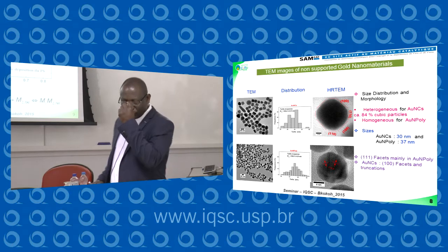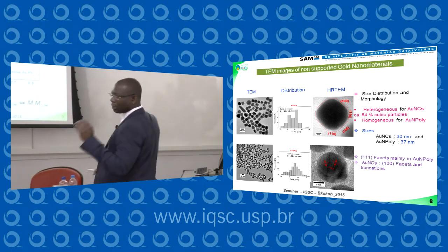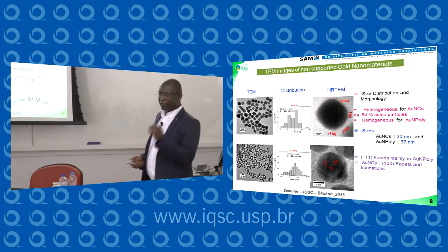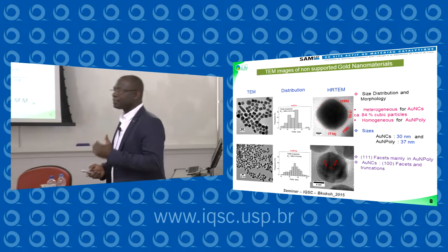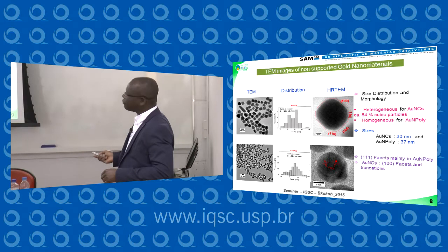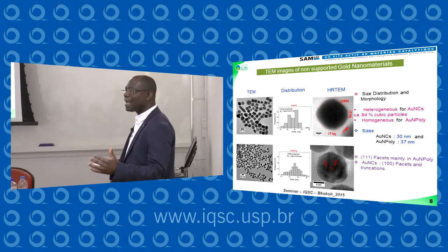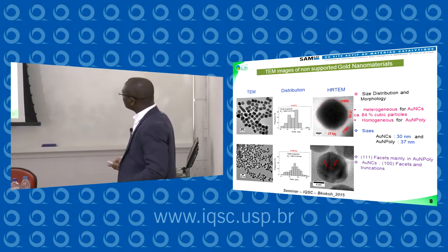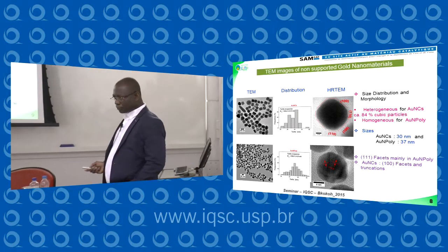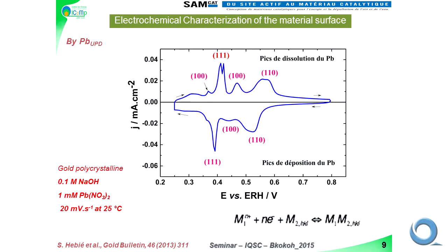It's the same in Alicante with Feliu. We take here, for example, a wire of gold, to reveal the orientation of the facets. This is the method of UPD, underpotential deposition of lead adatoms. By this method, you prepare this solution, and you apply a potential at 0.8. It's very important, because if you start here, you adsorb all the species at the surface, and you have to restart, okay? You prepare your working electrode, you immerse it in the solution at 0.8, and at the same time,